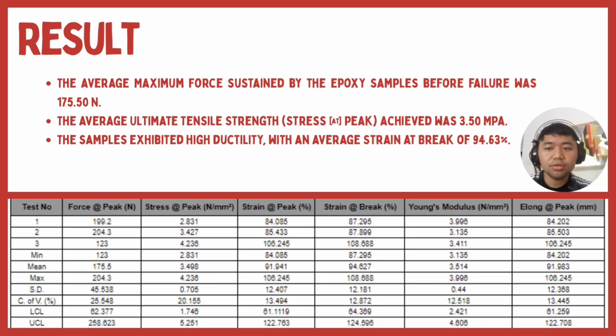Next, we will look into the raw data collected from the 3 test samples previously mentioned. Looking at the average, our epoxy sample sustained a maximum force of 175.50 newtons before failure. This translates to an ultimate tensile strength of 3.50 MPa. The most interesting data in the table is the strain at break. The samples show an average elongation of 94.63%.